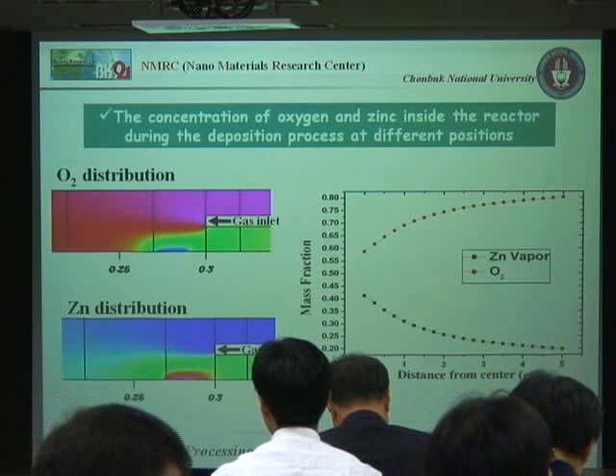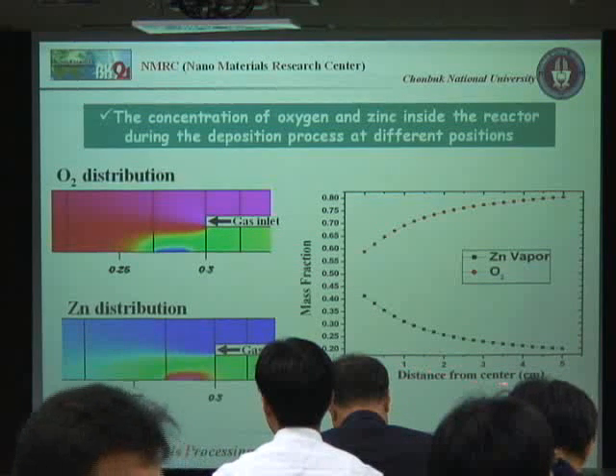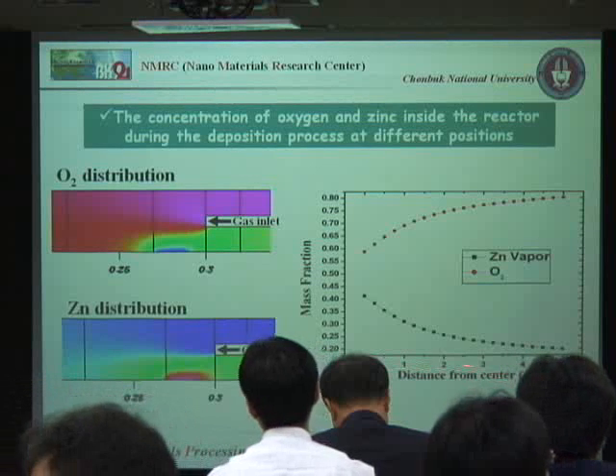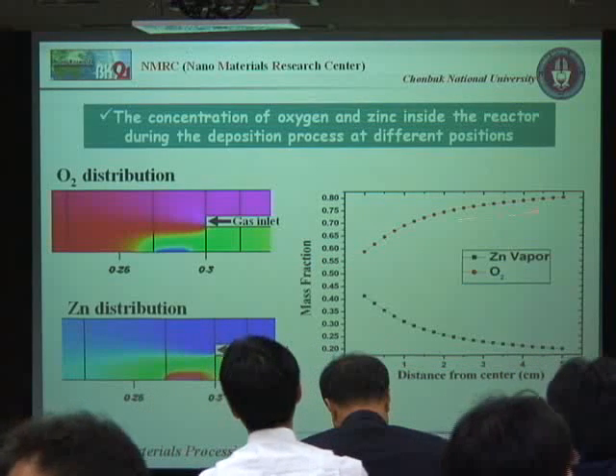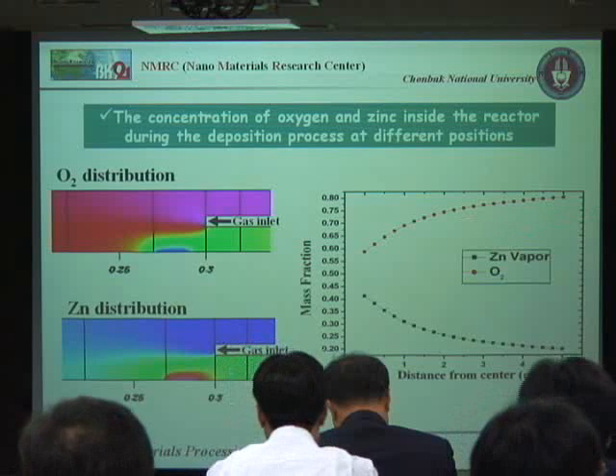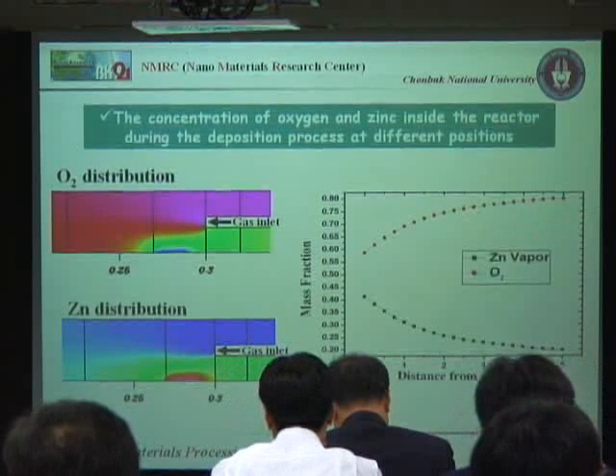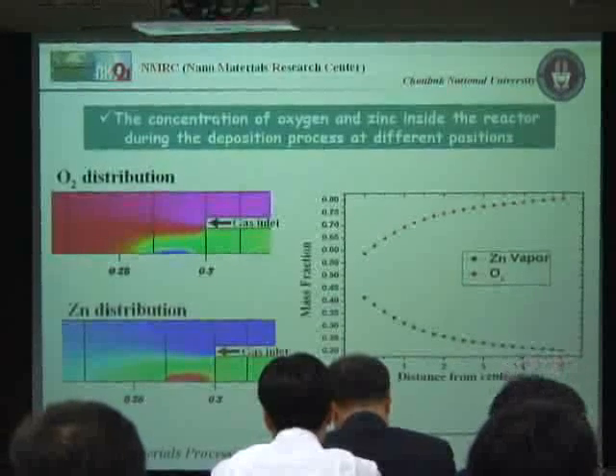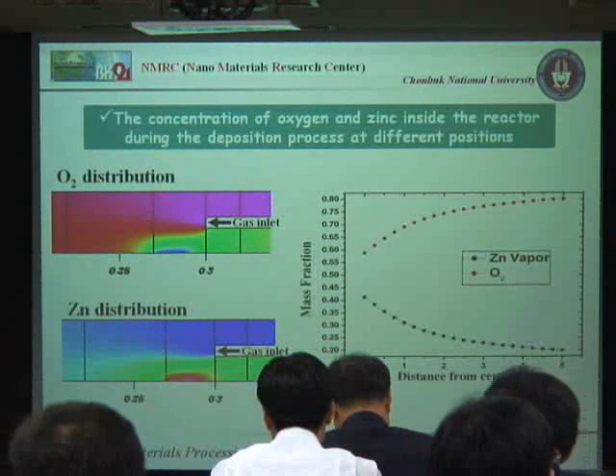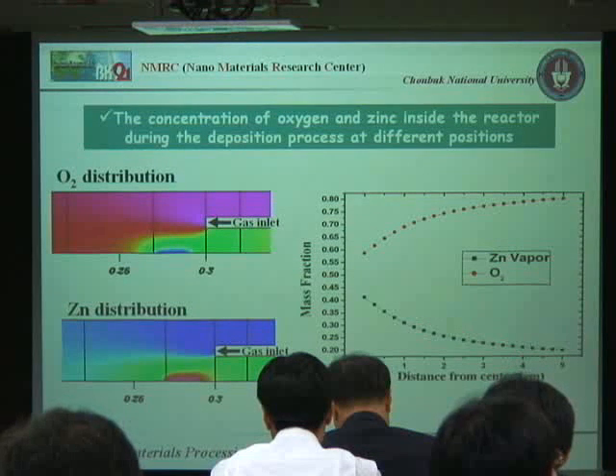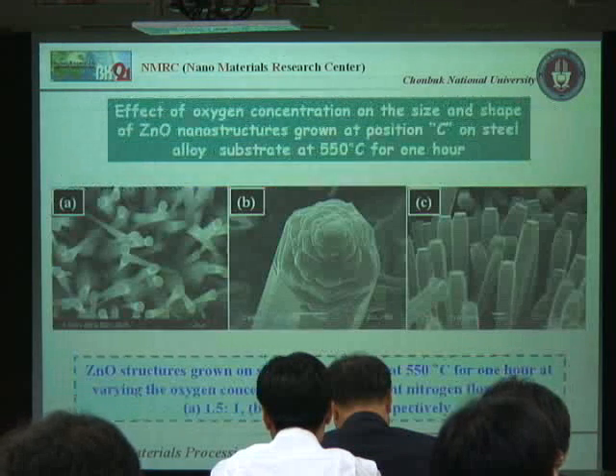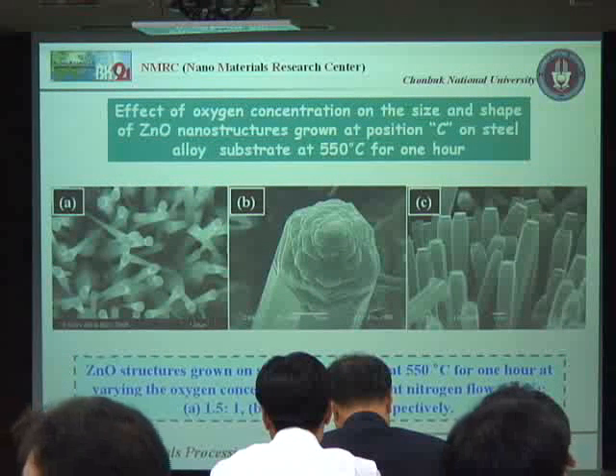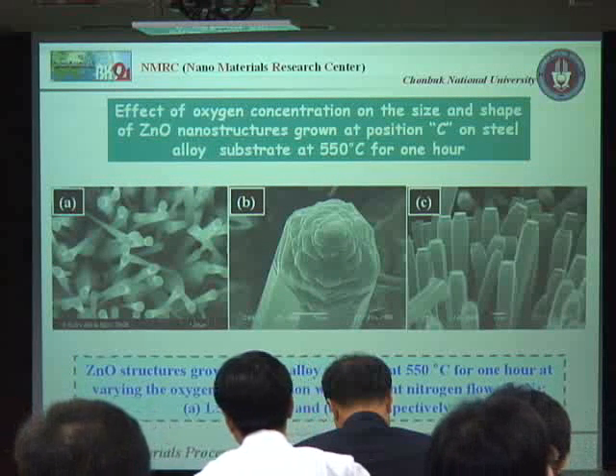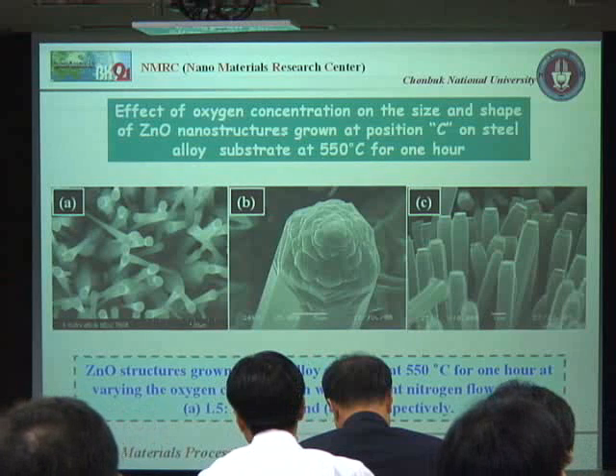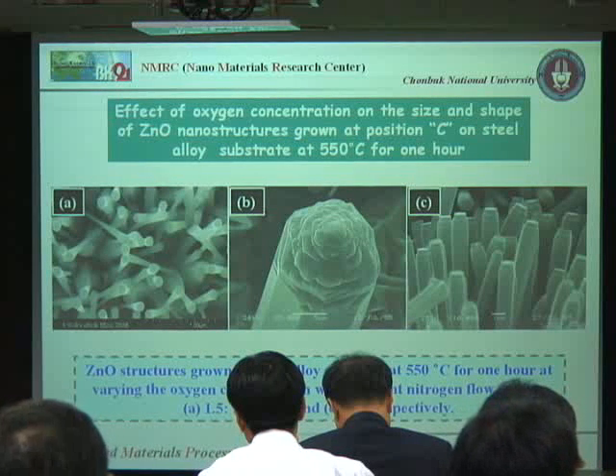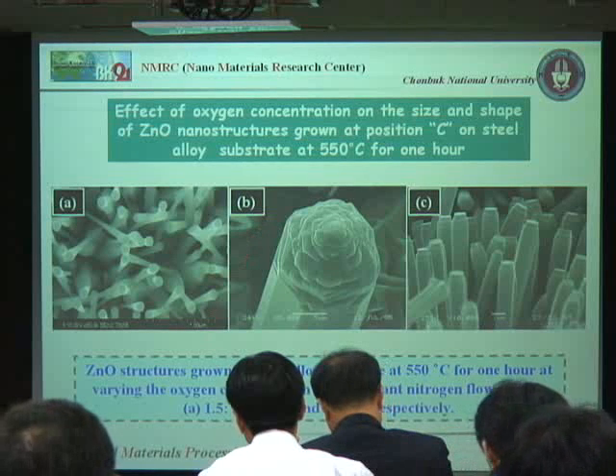To know the concentration of zinc and oxygen inside the reactor during the reaction process, we did some simulation, and we got that as the distance between the source material and the substrate increases, the oxygen concentration increases, while the zinc concentration is decreasing. So we also did some more experiments to verify whether we are getting the same results at different oxygen concentrations or not.